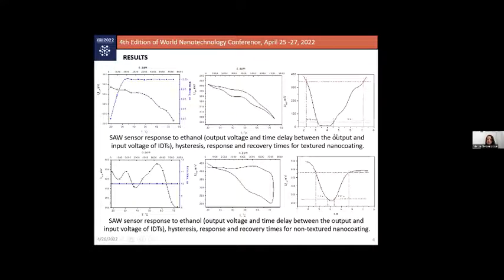The first row corresponds to the device with the textured nanocoating, and the second row to the non-textured one. As can be seen, there is a stable trend of output voltage decrease in line with the increase of the concentration of adsorbed analytes. The sensitivity is approximately 5 microvolts per ppm, with a very broad dynamic range from 0 to almost 7,000 ppm and a very small hysteresis, which introduces an error in the measurement of less than 1%.